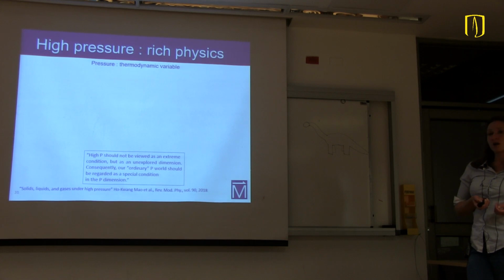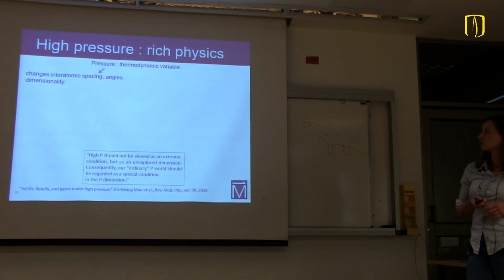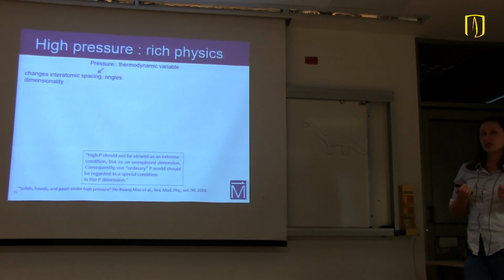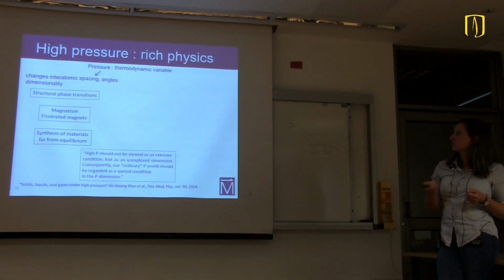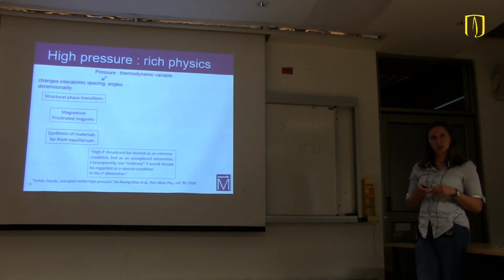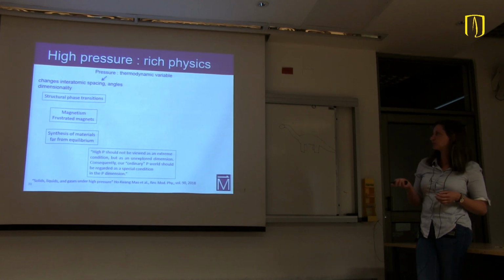So going back to condensed matter physics, which is what I do, pressure is again a thermodynamic variable. We can change various things when we compress a sample. We change the interatomic spacing. We bring the ions closer together. We can change the various angles also. This can trigger a structural phase transition. So we can go, for example, from body-centered cubic to a different crystallographic phase. It has an effect also on frustrated magnets. The frustrated magnet that I showed you earlier, SCBO, does very different things under pressure.